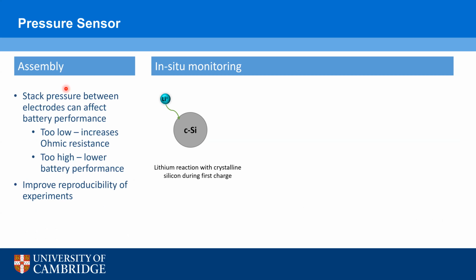So the first would be to try and improve the reproducibility of the experiments, because when you put together these 3 electrode cells, you typically have a plunger essentially to apply pressure between the anode and cathode. And this is because stack pressure is quite important when assembling these cells. If the stack pressure between the anode and cathode is too low, then we can increase ohmic resistances, and if it's too high, then it may lower the battery performance.